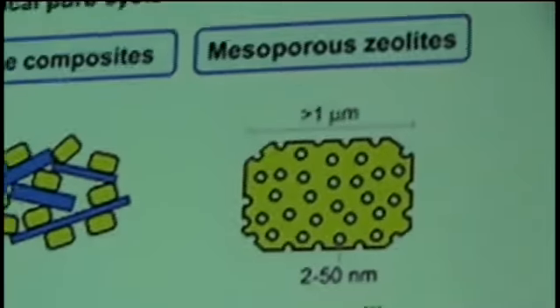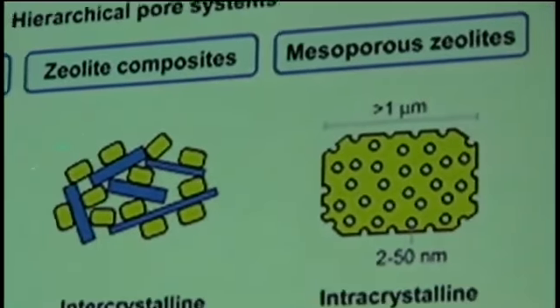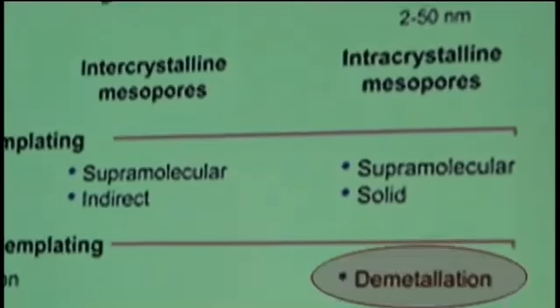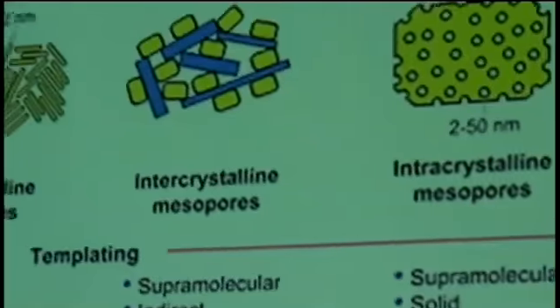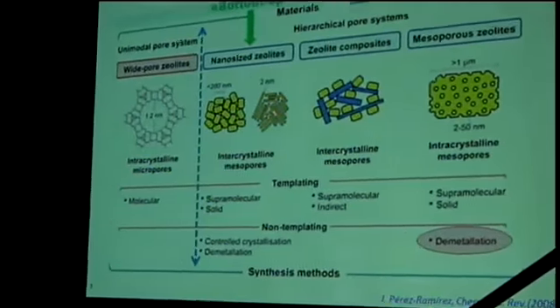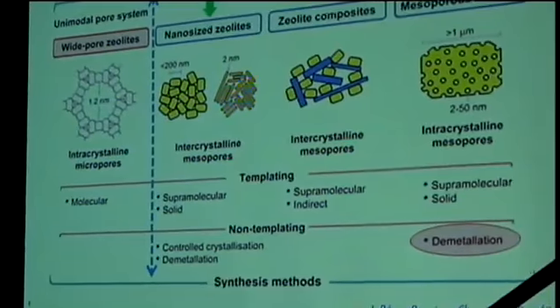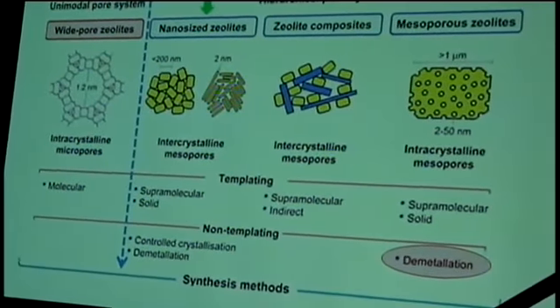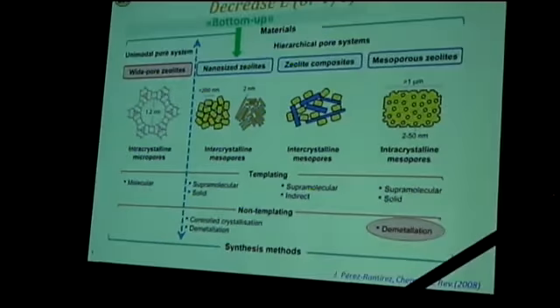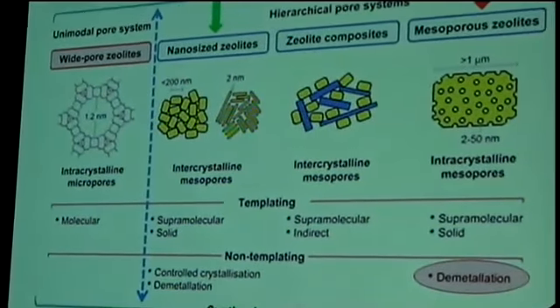For instance, you start to make nanozeolites from the start, or in fact, the Topse way, where you try to force the growth of small crystals by spreading the crystals apart or having them transferred by carbon nanotubes or whatever. I will not talk about that. And then you have top-down approaches, where basically you take an existing material and you drill holes inside this existing material, so you don't have all the problems of the processing of these things.